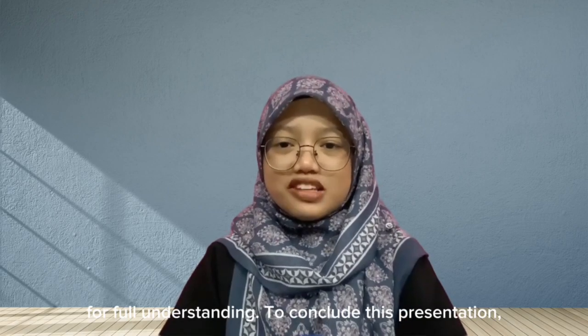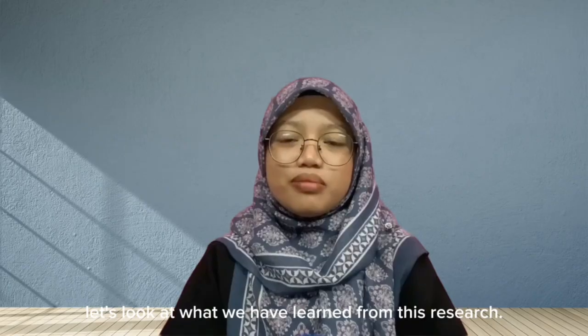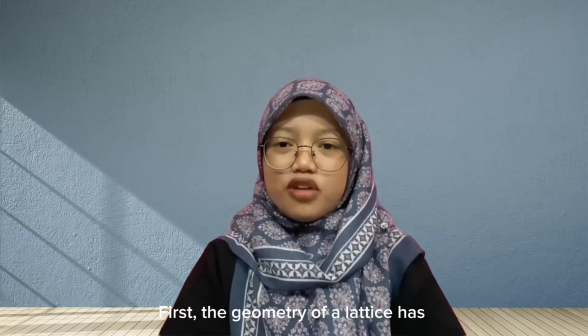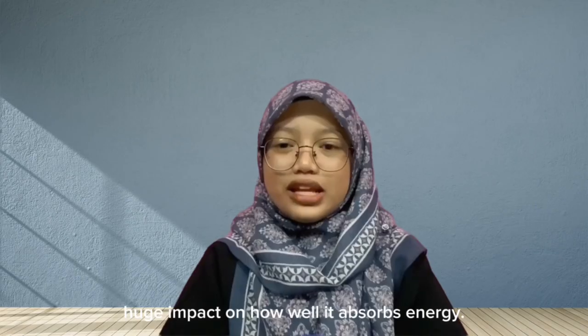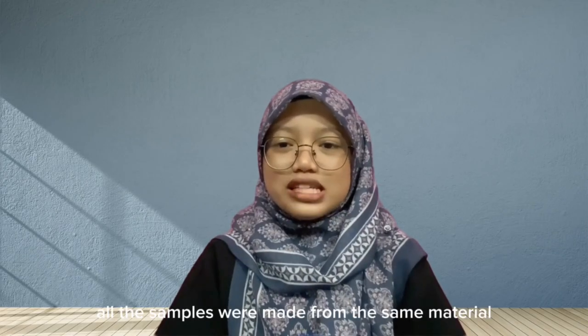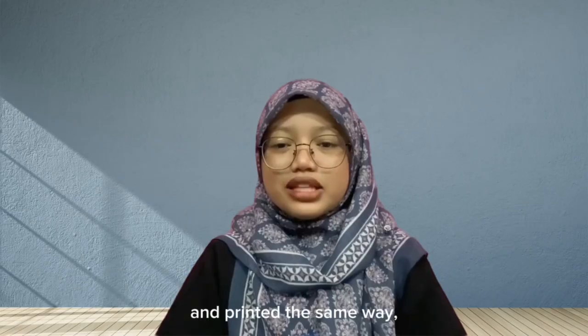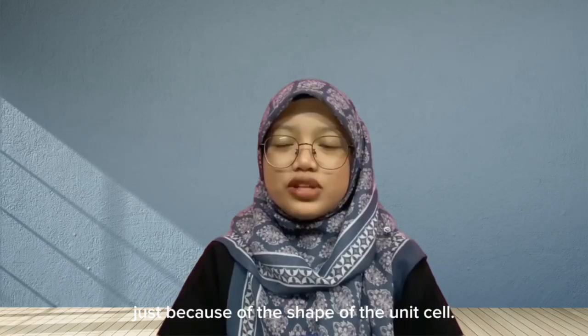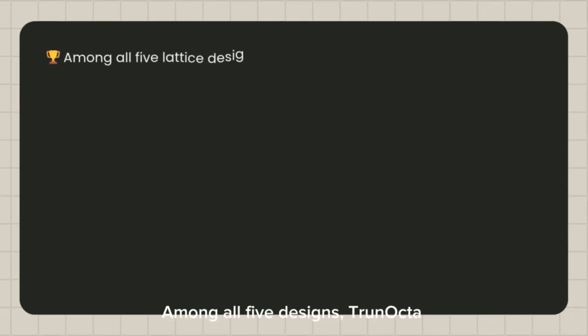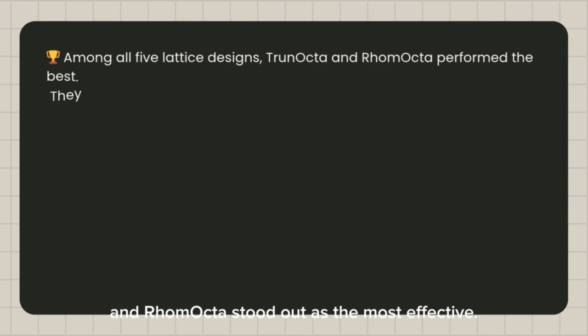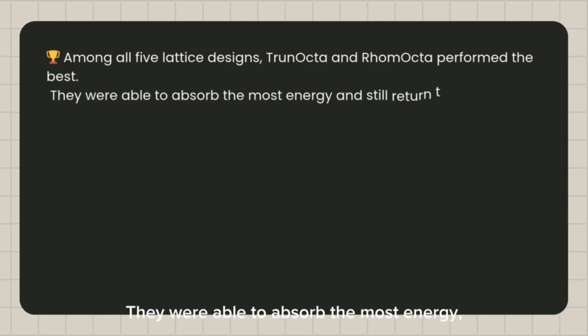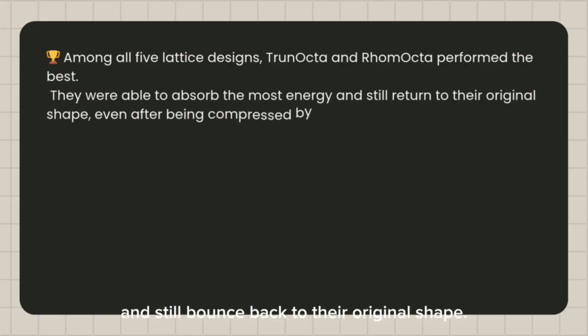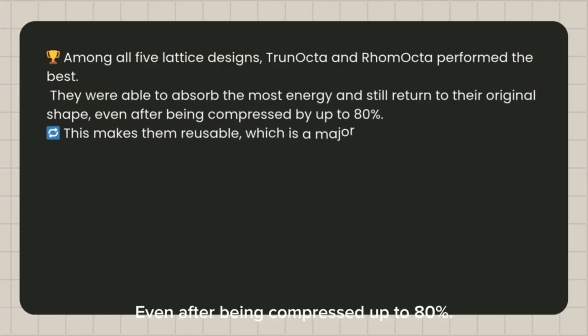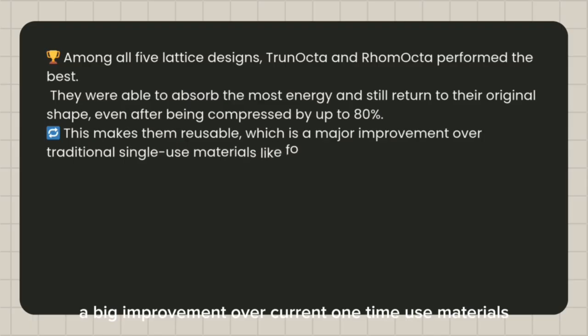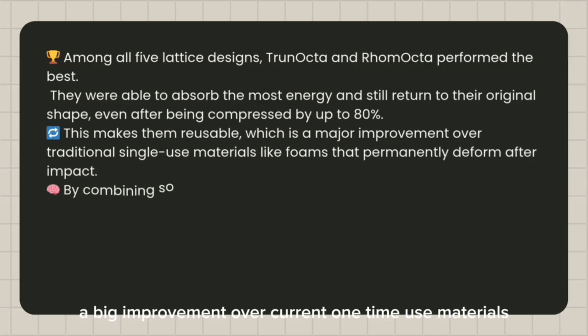To conclude this presentation, let's look at what we have learned from this research. First, the geometry of a lattice has a huge impact on how well it absorbs energy. Even though all the samples were made from the same material and printed the same way, their performance was very different just because of the shape of the unit cell. Among all 5 designs, TrunOcta and RhomOcta stood out as the most effective. They were able to absorb the most energy and still bounce back to their original shape, even after being compressed up to 80%. That makes them reusable, a big improvement over current one-time use materials like foams.